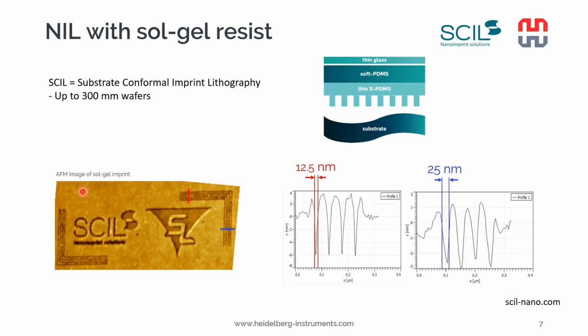In this case, we have used a 2D pattern. We have just made some very high resolution structures to test the maximum resolution that we can achieve. And we were able to reproduce these 12.5 nanometer wide lines very accurately in the imprint here. They are using a special sol-gel resist for their process.